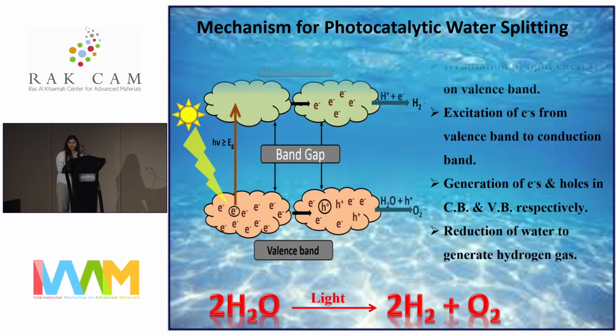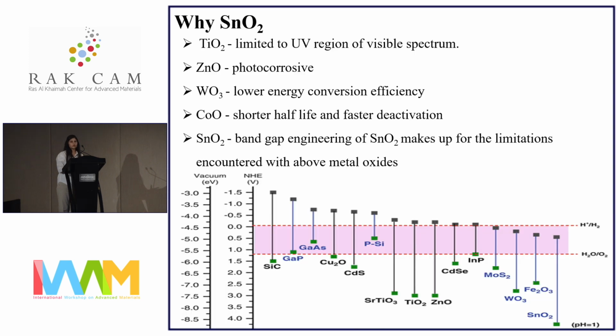Coming on to the mechanism for photocatalytic water splitting. Basically, when a semiconductor is irradiated with light energy which is equal to or greater than the band gap of the semiconductor, then the electrons are excited from the valence band of the semiconductor to the conduction band. This leads to the formation of photo-generated holes and electrons in the valence and conduction band respectively. Finally, the photo-generated carriers are transferred to the surface to carry out the reduction and oxidation processes to generate hydrogen and oxygen gases.